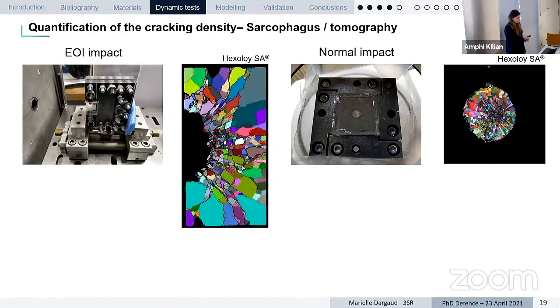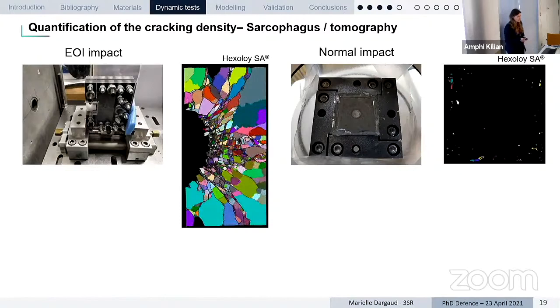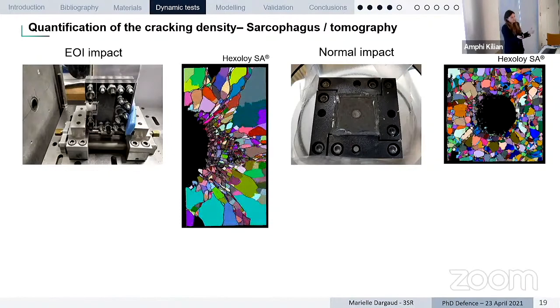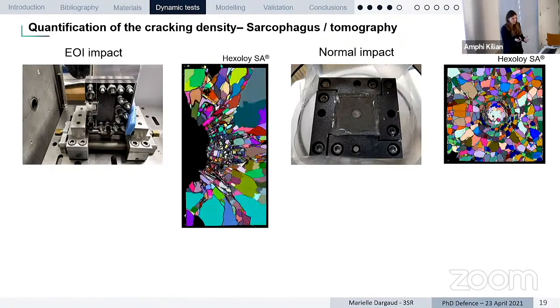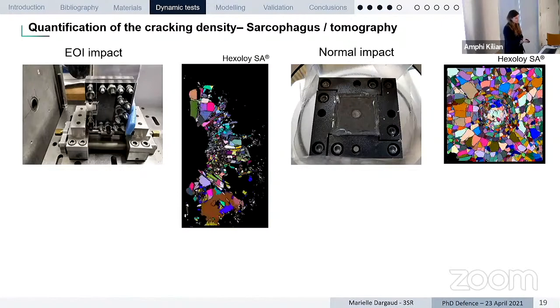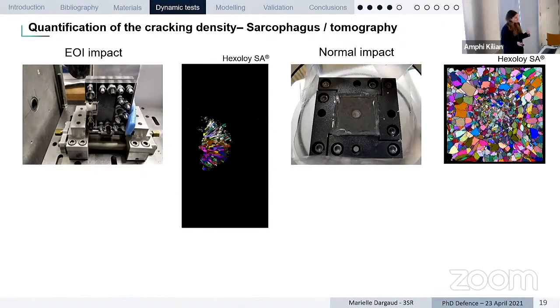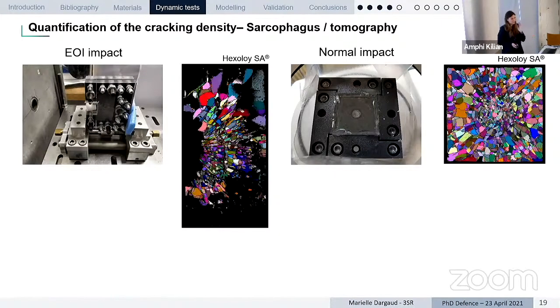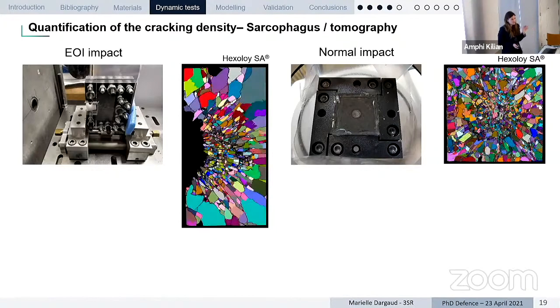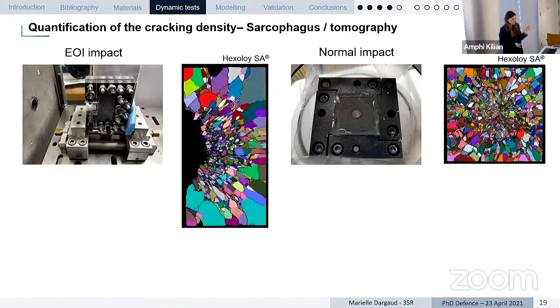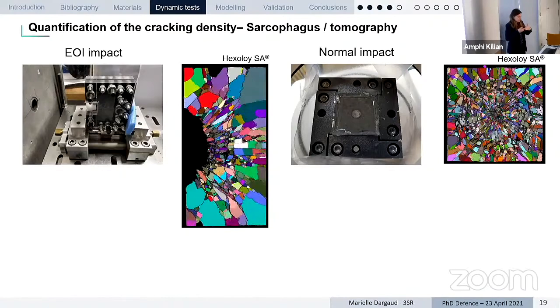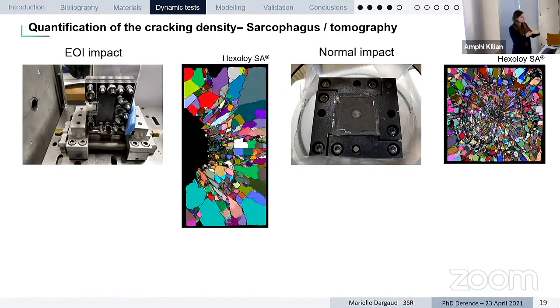These two post-mortem samples could be observed through X-ray tomography analysis. Here you have some images of a 3D volume of the post-mortem sample captured from X-ray tomography, which was post-processed so that we could identify the cracks and individualize the different fragments. Here we have a view where we are going through the sample for the two configurations.